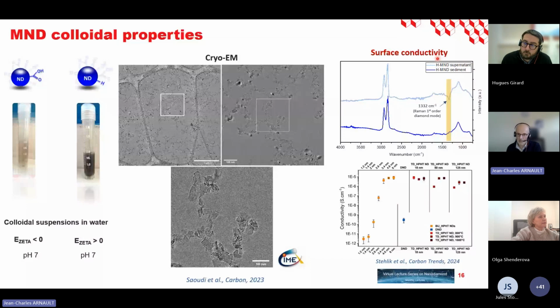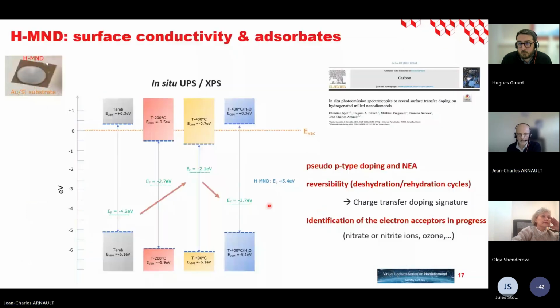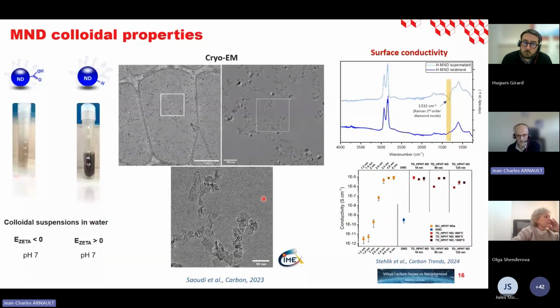And this was confirmed by measurements from the Prague group, at about the same period. And you can see here the conductivity measured for different nanodiamonds. So HPHT milled particles of different sizes, hydrogenated, compared to detonation hydrogenated. And you see that if you consider the hydrogenated detonation nanodiamond, you lose this surface conductivity by more than 4 orders of magnitude. So this is interesting for us. It suggests some surface transfer doping.